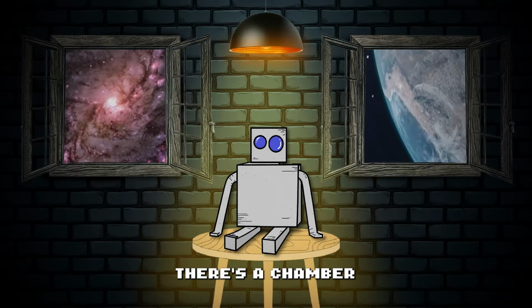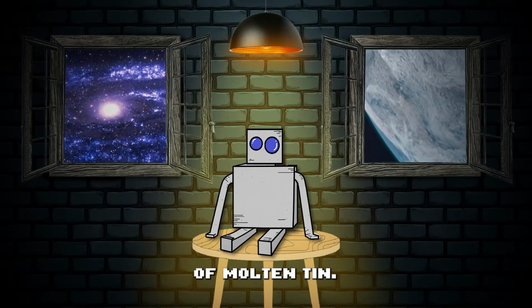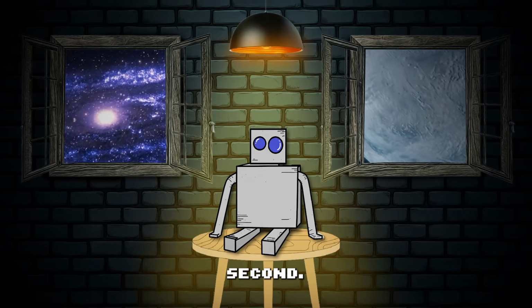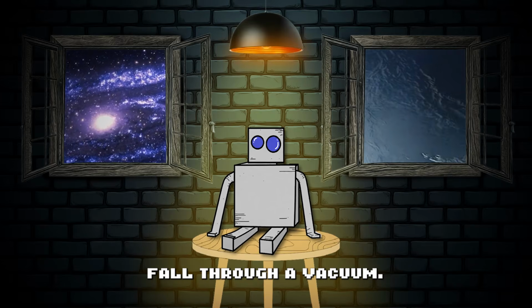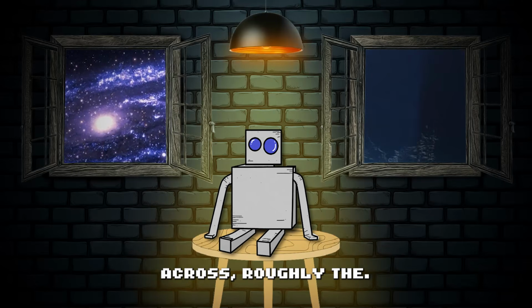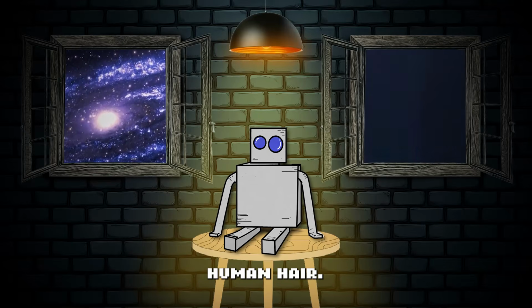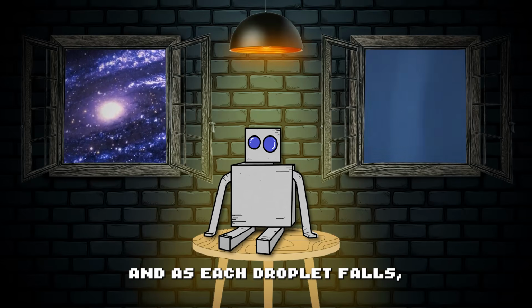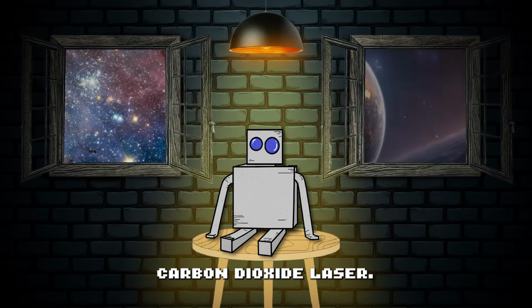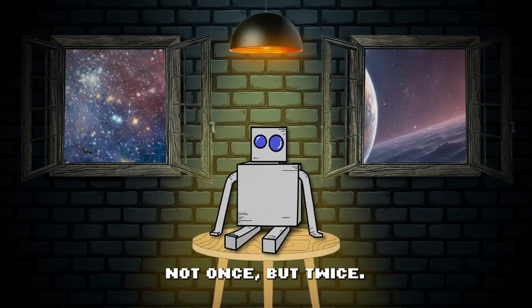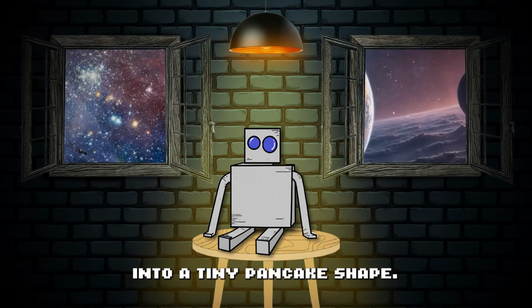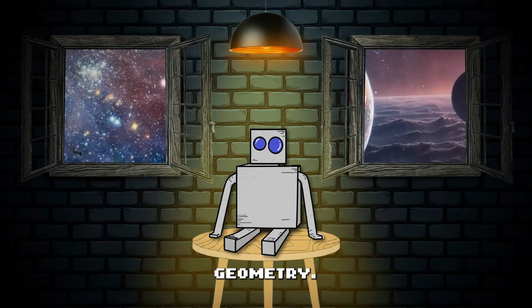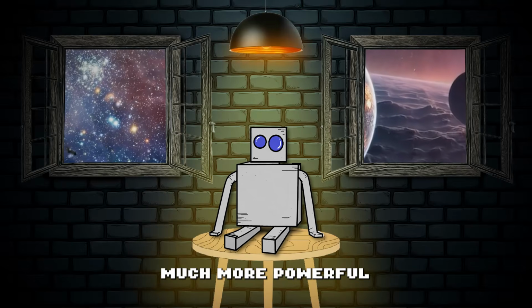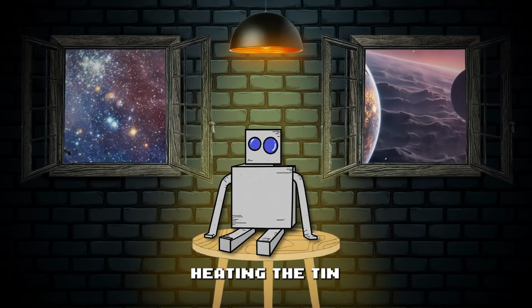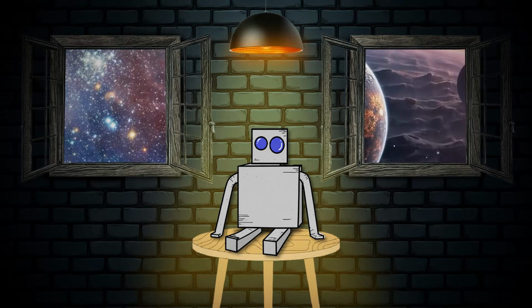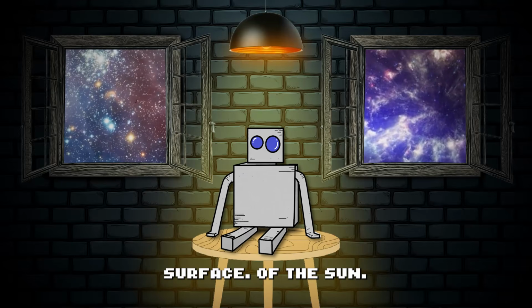Inside the machine, there's a chamber where tiny droplets of molten tin, we're talking about 50,000 droplets per second, fall through a vacuum. Each droplet is about 25 micrometers across, roughly the diameter of a thin human hair. And as each droplet falls, it gets hit by a pulse from a high-powered carbon dioxide laser. Not once, but twice. The first pulse flattens the droplet into a tiny pancake shape, which optimizes its geometry. Then a second, much more powerful pulse vaporizes it, heating the tin to around 500,000 degrees. That's roughly 40 times hotter than the surface of the sun.